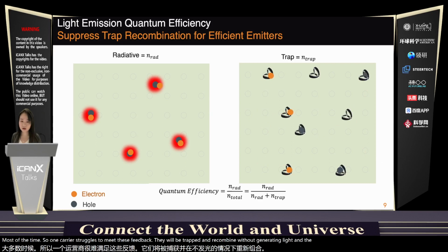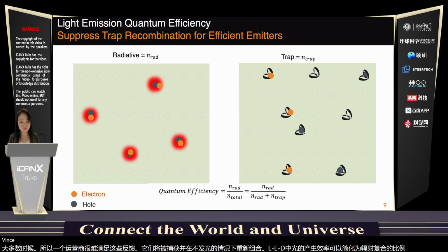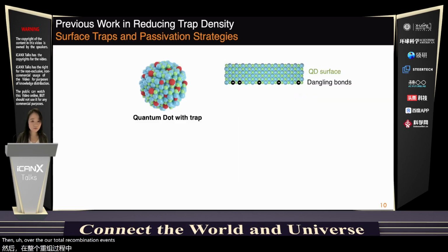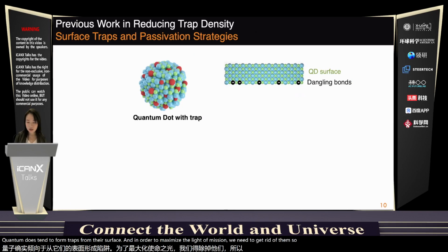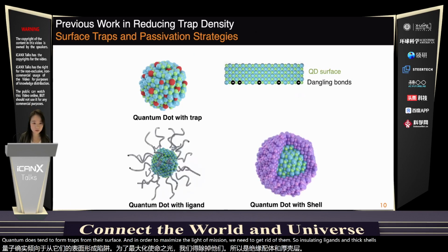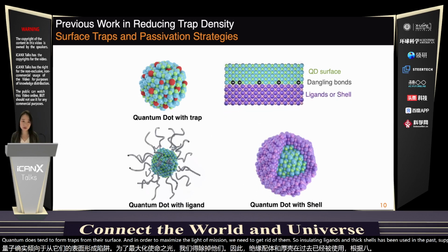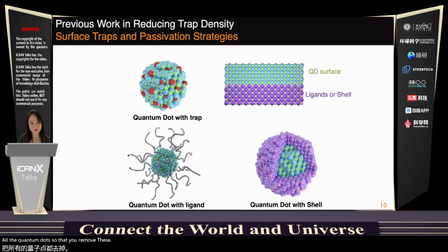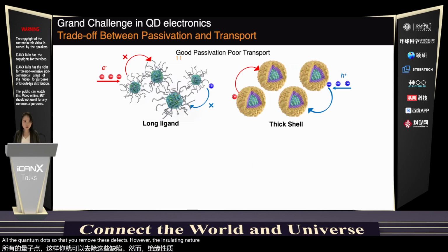The efficiency of light generation in an LED can be simplified as the ratio of the radiative recombination events over the total recombination events. As mentioned earlier, quantum dots tend to form traps on their surface, and in order to maximize the light emission, we need to get rid of them. So insulating ligands and thick shells have been used in the past to coordinate with the surface atoms of the quantum dots so as to remove these defects. However, the insulating nature of these long ligands and thick shells compromises the charge transport, meaning that higher voltage and higher power will be needed to drive the same amount of current through the device.